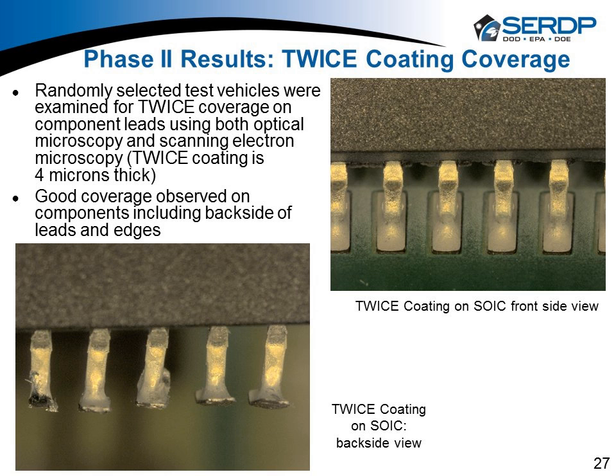The one thing we did, this picture on the lower left, I actually went in and we cut the pads off the board. Didn't want to cut up here. I wanted to try to keep the surface intact. And what you can see here, it doesn't show up as well as I'd like, but the nice milky ghosting coating view, the observation, that's the TWICE coating on the backside. So one, the coating tends to go and cover areas that conventional coatings don't cover very well. And two, because of our setup, we can spray in at different angles, and we have better spray penetration trying to come in and spray, say, at the backside or on this toe or from the top side. Just the nature of the coating lends itself to being applied with better coverage than some of the conventional coatings.